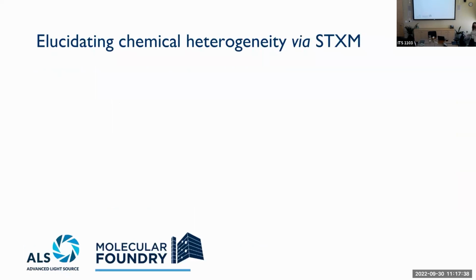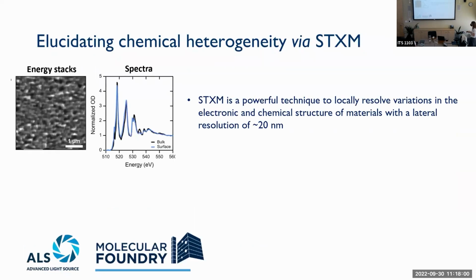So I told you about morphology, I told you about functionality. However, there is another important part in all of this, which is chemistry. And possibly chemical mapping of elements in the material to tell you more about the degradation. So we utilized scanning transmission X-ray microscopy, and scanning transmission X-ray microscopy is a technique that is available at the Advanced Light Source. It allows you to take an X-ray absorption spectrum at a spot with a spatial resolution that is 20 nanometers. And in this case, we're looking at the vanadium and the oxygen edge of the bismuth vanadate, and then we can understand how these X-ray absorptions change over time when we test the material.